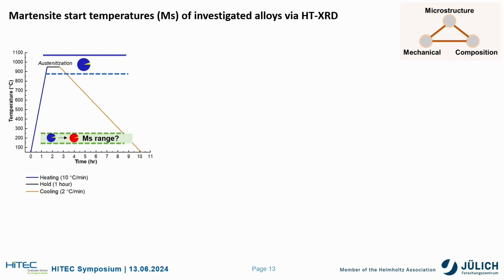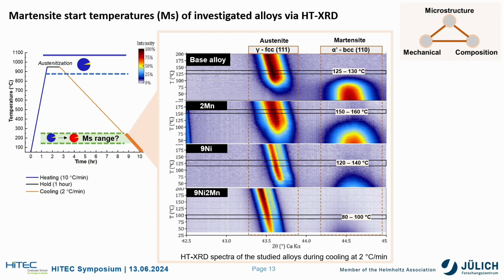Next question, where is Ms, or the martensite start temperature? We can determine this via the technique called high temperature XRD, wherein we record the temperatures at which the martensite BCC peaks start to form during cooling. And according to this graph, the Ms ranges are all slightly above room temperature. But the intensity of these martensite BCC peaks forming as a function of temperature varied significantly across these investigated alloys. This intensity is correlated to the amount of martensite forming as a function of temperature.